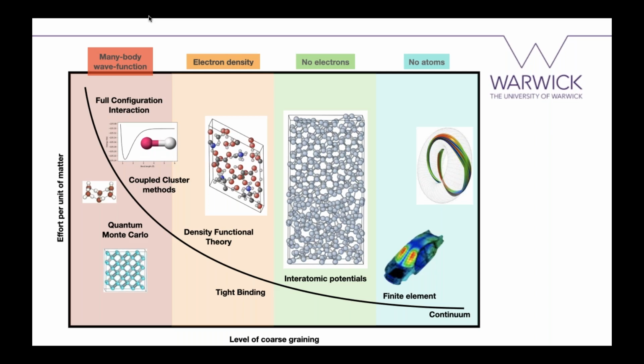So this cartoon tries to represent a few typical computational techniques that people use to model materials on different scales. On the horizontal axis, I have this measure of coarse graining. As you go from left to right, you go from the smallest details of the electronic structure on the wave function level, and then go to density functional theory, where only the electronic density is considered. You arrive at interatomic potentials, where electrons are coarse grained, and you end up with finite element where you don't even consider atoms.